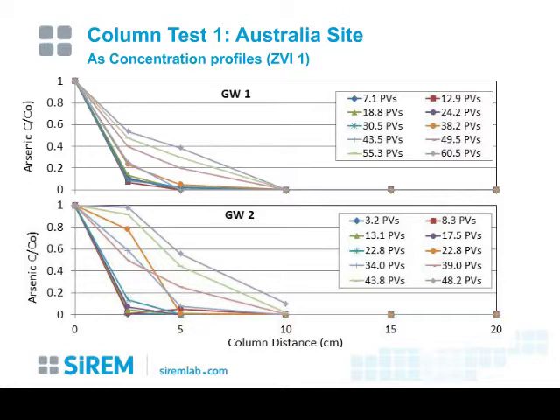So the results are shown for one iron type but 2 different groundwaters. And this was the better performing iron. Just for the sake of time, I'm not going to show all the results. What's shown is the C over C naught, so the concentration change over 10 profiles with increasing volume of water. And so these are essentially breakthrough curves. As you see, the iron is getting used up or passivated, and so we see a progression of arsenic profiles. Arsenic 5 gets reduced to arsenic 3 and then complexes with iron and creates solid phases. So it creates passivation because it blocks the iron surfaces and doesn't allow it to be reactive any longer.